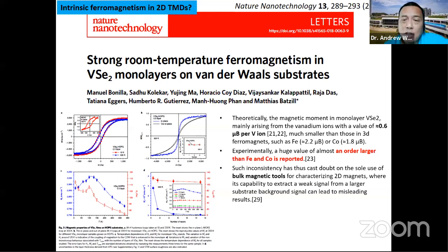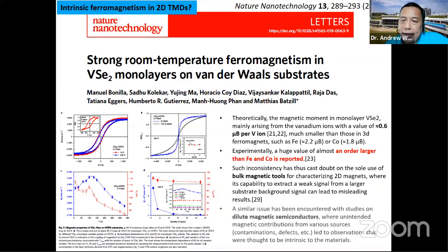And this inconsistency did cast doubt on the use of bulk magnetic tools for measuring this ferromagnetism, because in this case, you're measuring everything from the substrate and any contaminants and so on. And this brings to mind the field of dilute magnetic semiconductors, where many people reported magnetic materials where this magnetism was caused by extrinsic contamination or defects.